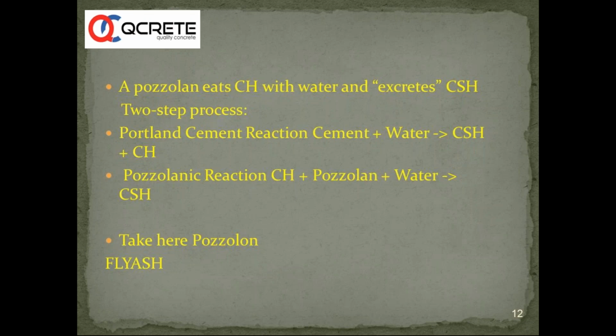So here we are talking about this pozzolanic fly ash. This reaction is also called secondary hydration. The initial hydration is between cement and water, giving rise to calcium silicate hydrate gel and calcium hydroxide. The secondary reaction is the SiO2 of fly ash reacting with calcium hydroxide, consuming calcium hydroxide and forming more calcium silicate hydrate gel. The amount of calcium hydroxide is reduced, and denser concrete is made.